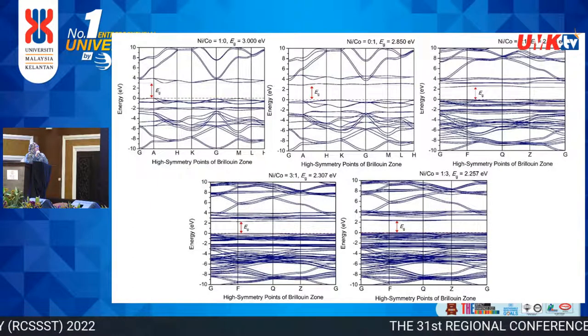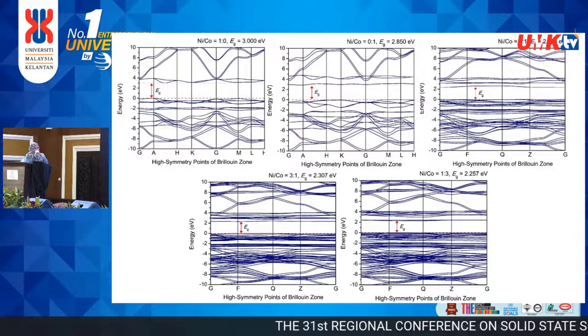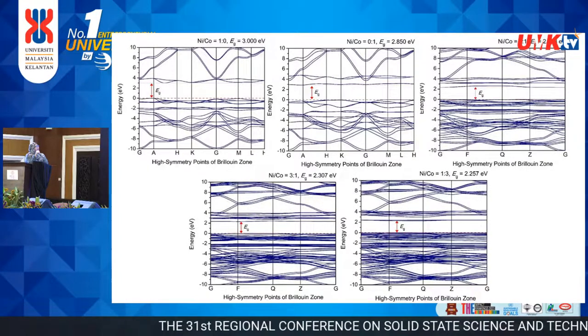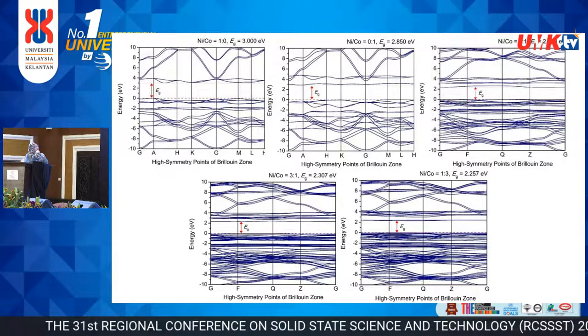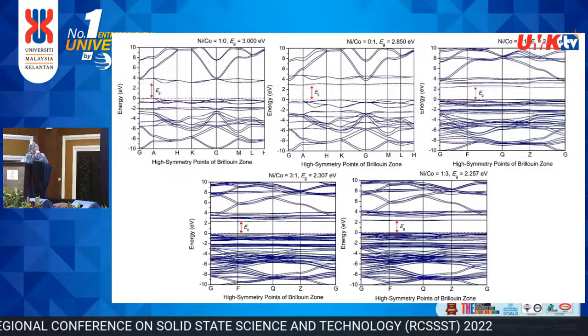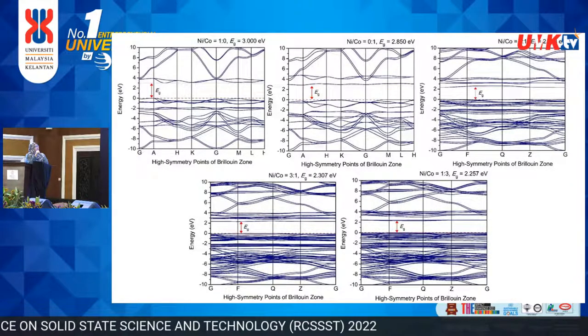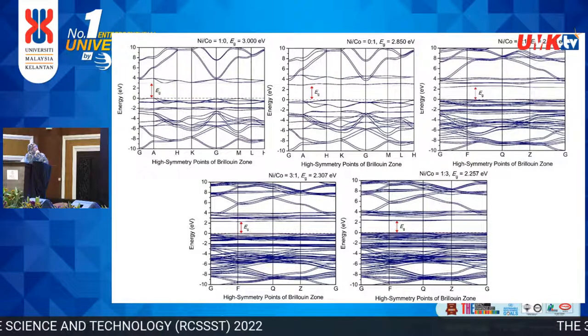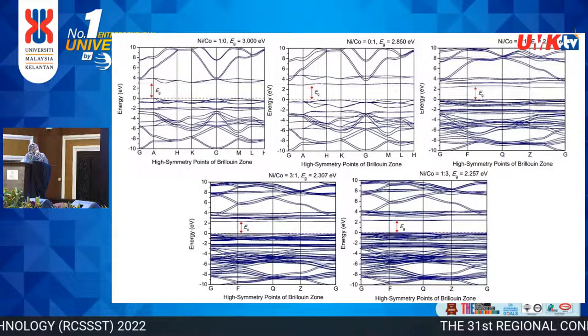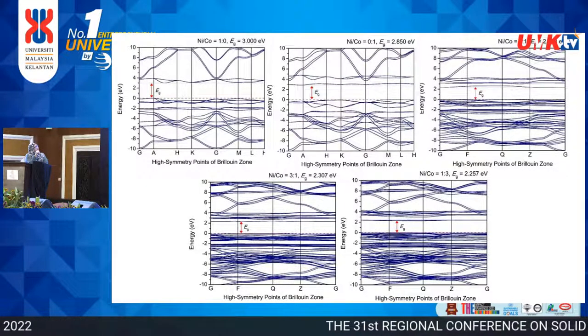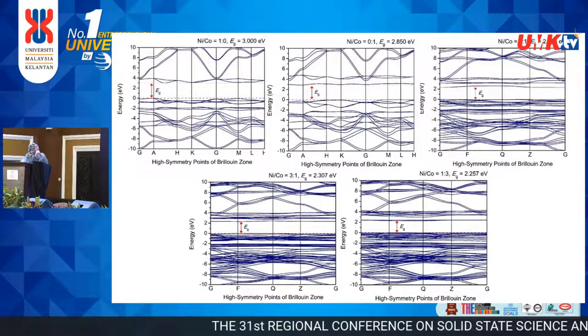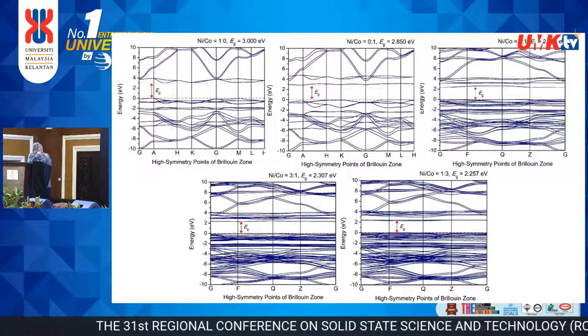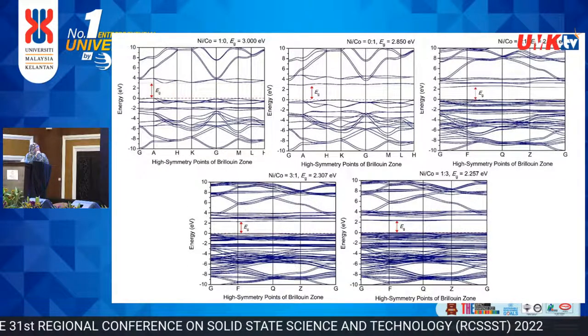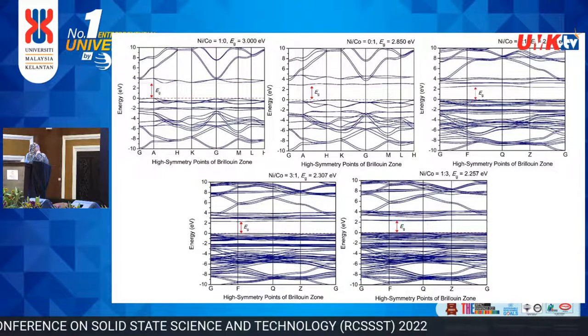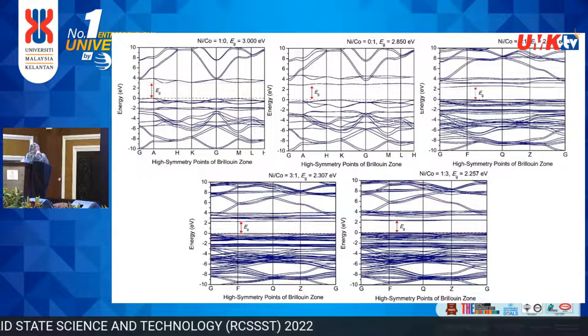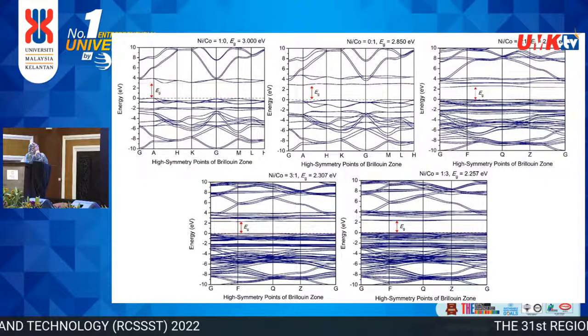So this is the band structure. You can see that by adding cobalt to nickel, the electronic band gap reduces. Then we get the smallest band gap at nickel to cobalt ratio 1:3, 2.257 electron volt.